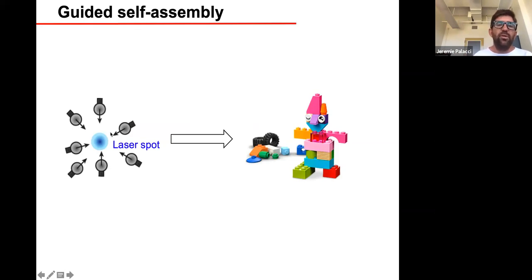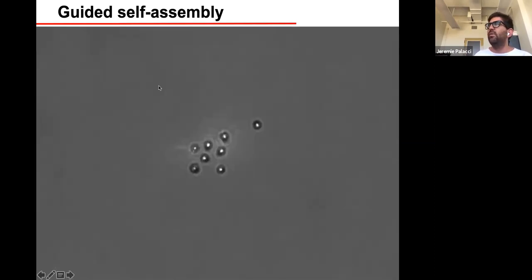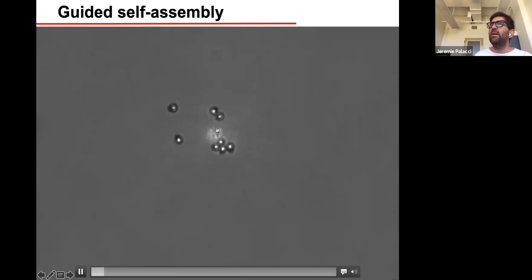So we start with a dilute suspension of those particles. Why do we do dilute? Because if we take too many of those particles and the density is high, then they will run into each other and do a motility-induced phase separation, which is a completely different type of physics we didn't want to study. So we start dilute, and because all the particles travel towards the laser spot, you will get a local concentration, and we'll see what happens in a second. We shine a laser spot, we see that they all travel towards it, and they collide, and then they break down, they make something, and then they break down.